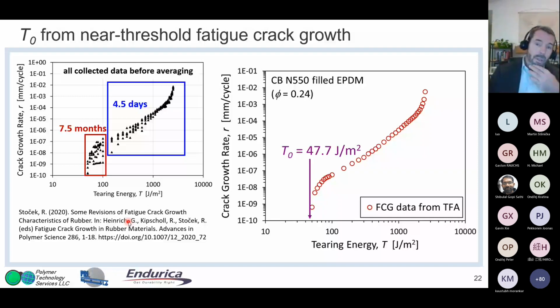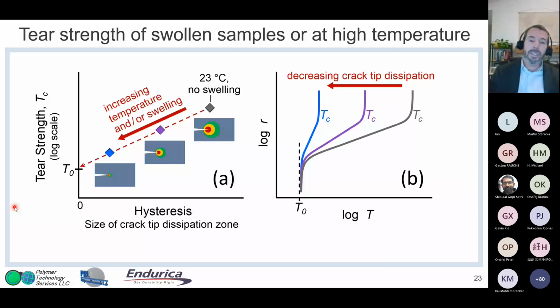One method that folks have used to, again, try to minimize the dissipation at the crack tip is to either use swelling, so you can swell the sample, or you could heat up the sample. It's well known in filled rubber, in particular, that hysteresis goes down as you go up in temperature. Hot tear is lower strength than room temperature tear, right? That's what we're saying here. You do room temperature tear and you do hot tear at some increasing temperature. And if you plotted this versus some measure of dissipation, you could extrapolate to T0. So either through swelling or through increased temperature.